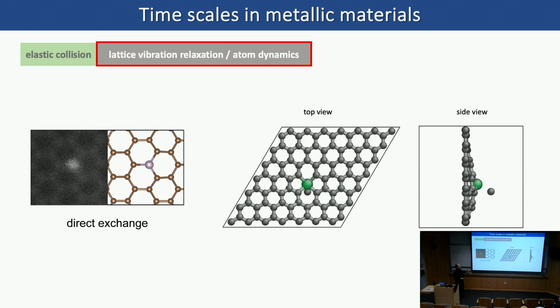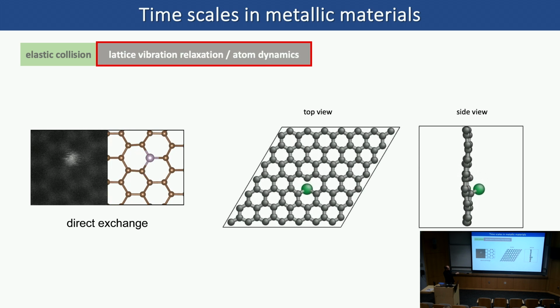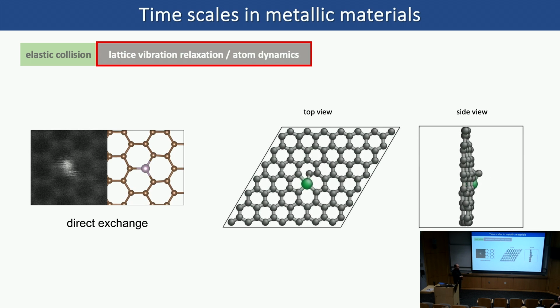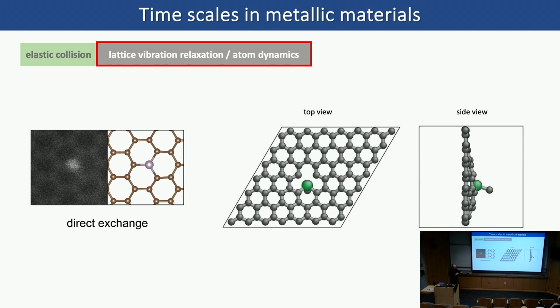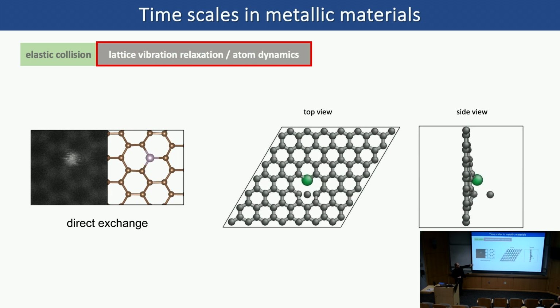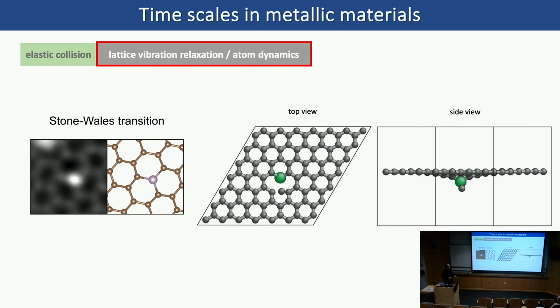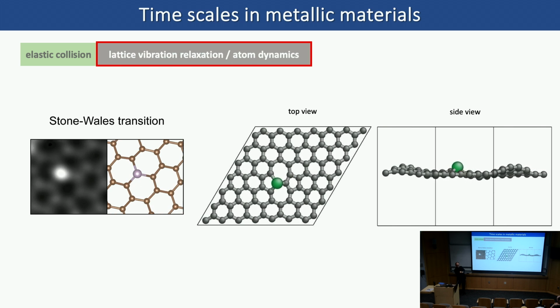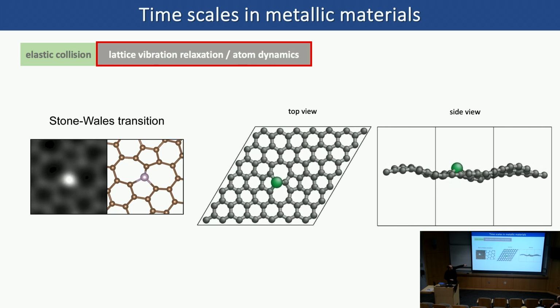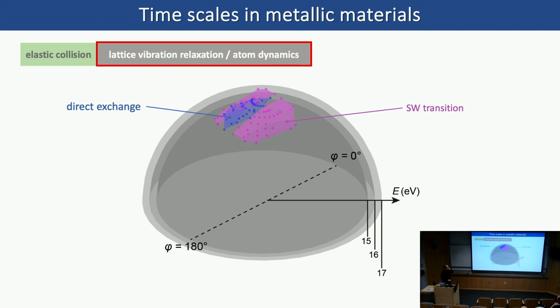How can we simulate that? There's actually one way to simulate that. That is by using ab initio molecular dynamics. So in this case, we could recover the direct exchange scenario where you have those two atoms exchange their sites. Once you give this carbon atom an initial kick and let it just evolve, you could see that the carbon just goes around, and then this phosphorus atom actually bounces down, and then they switch their sites. So we could use ab initio molecular dynamics to reproduce what we're seeing inside an electron microscope. And the same thing goes for the Stone-Wales transition. If the carbon atom is kicked a little bit sideways, you could also lead to this Stone-Wales transition. So in this case, it's a pure ab initio calculation, and it shows what we observed here. All right. So now what you can do is you sample the space.